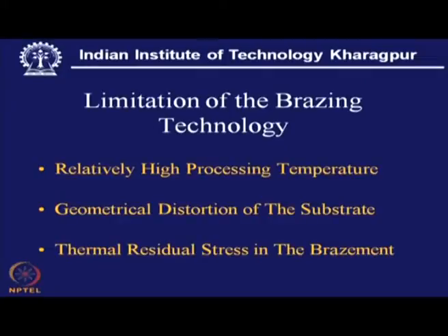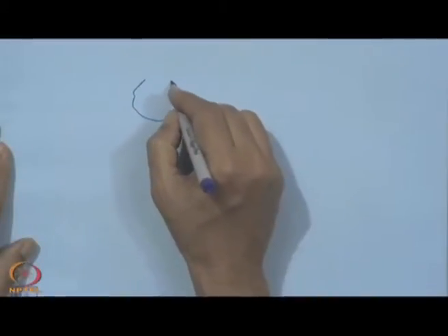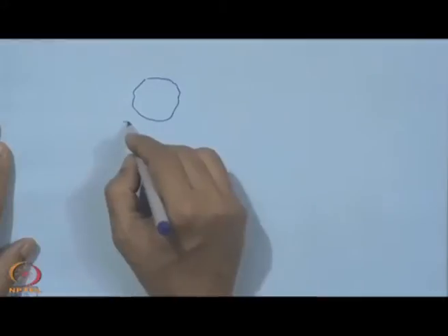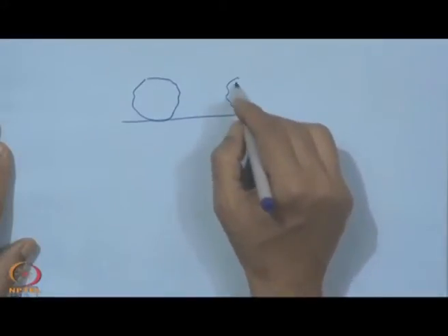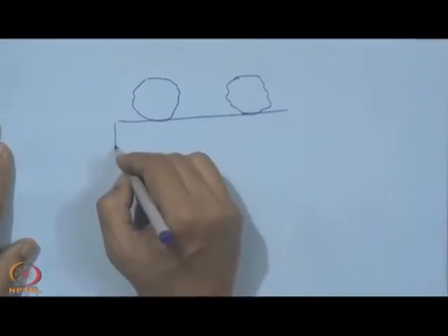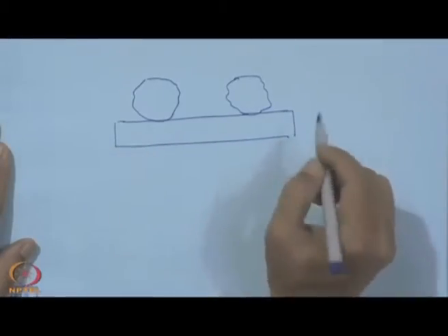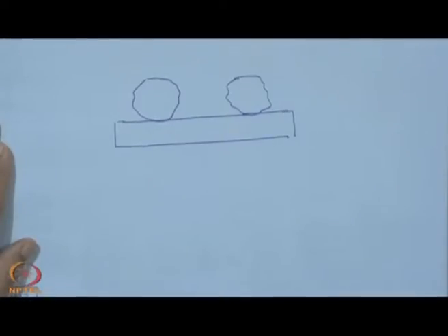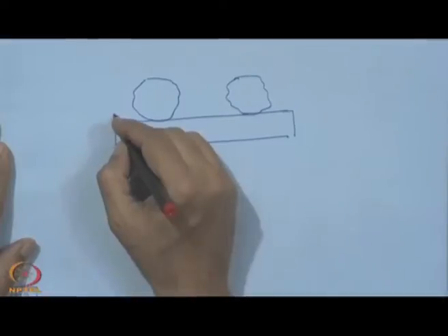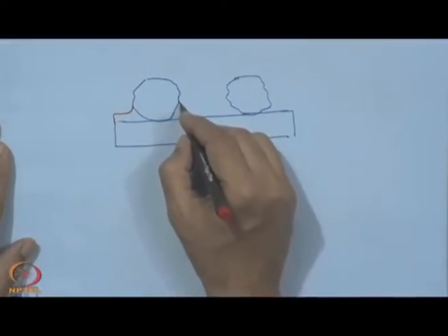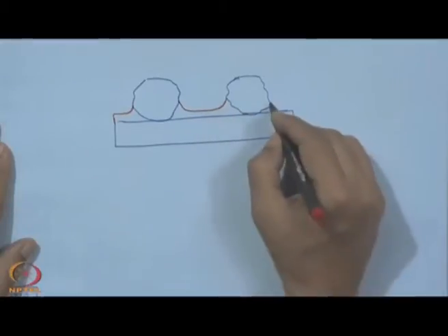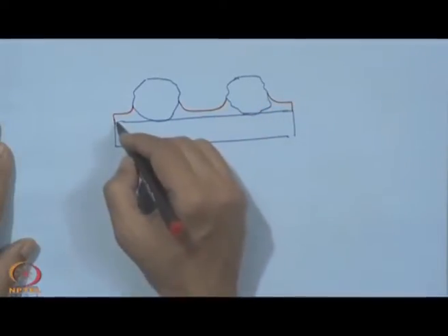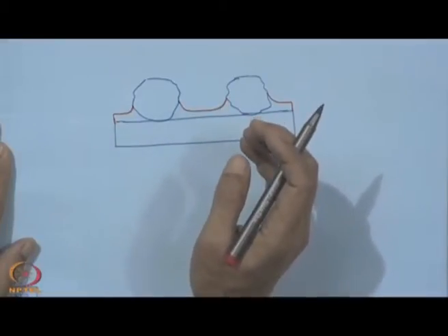And then most importantly, the thermal residual stress, and this is a very important issue one has to care for. It can be illustrated by this simple sketch. This is one grit, this is the second one, and they are supported by the substrate material, and here we have the braze alloy, and this braze alloy, by effective wetting, will give this shape. That is one of the special features of brazing.